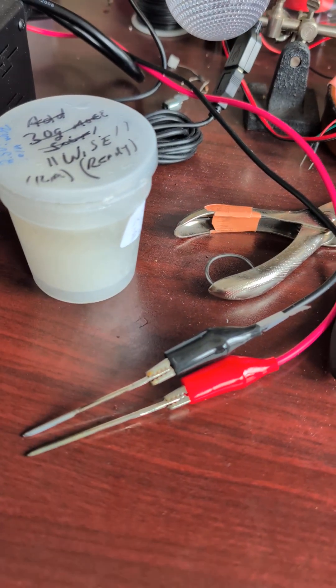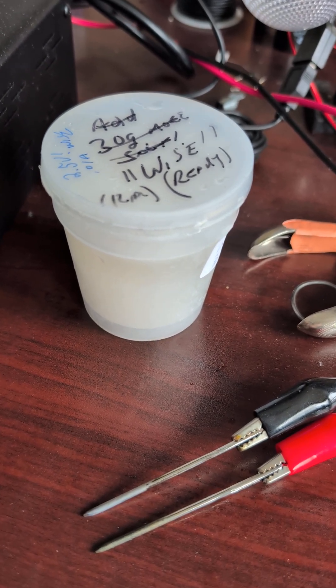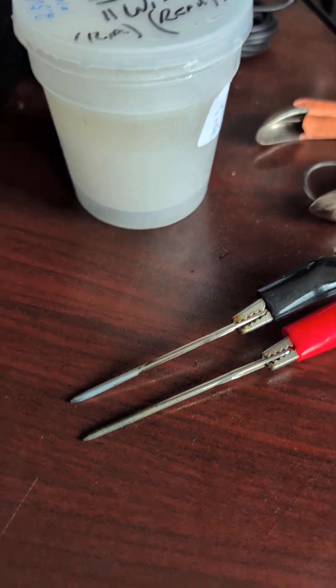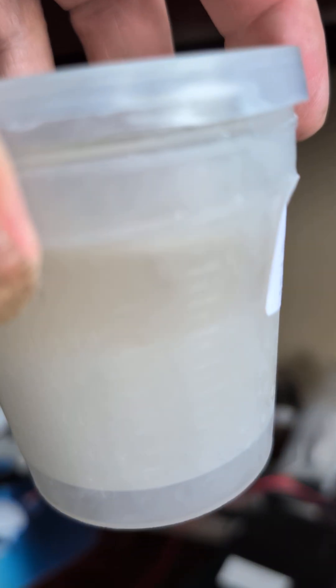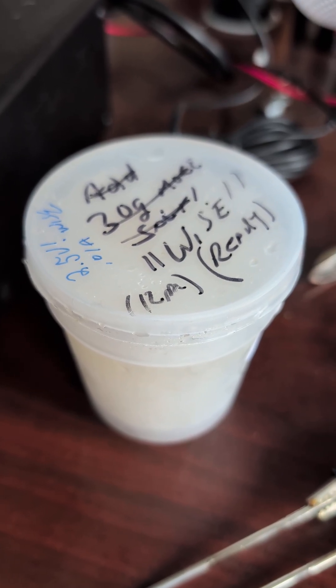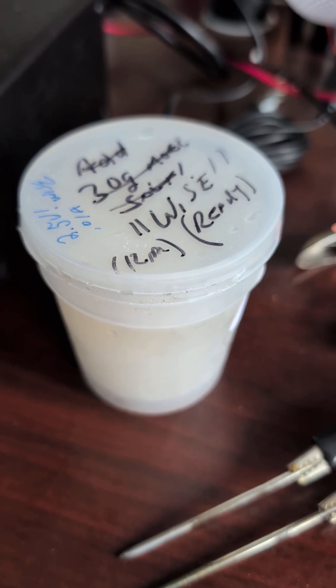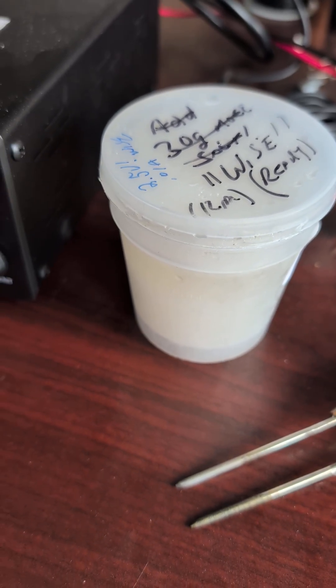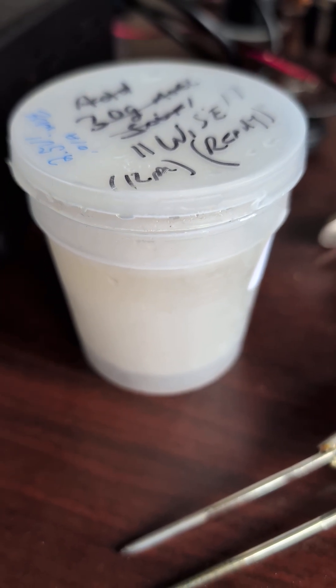Using a power supply with a couple of stainless steel pins as electrodes: if I put that into a dilute sodium chloride salt water solution and go to 1.7 or 2.0 volts, I start to produce hydrogen and oxygen gases. But if I clean these electrodes and put them in some of this WISE, I've reached 2.5 volts with no gas evolution observed. I do get a deposit of solid salt on the anode — we'll be studying that — but there's no gas evolution that I can see visibly.